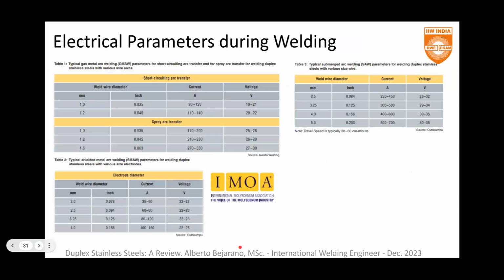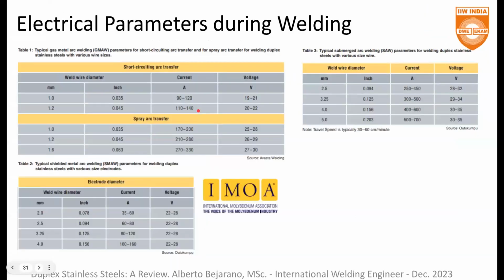About the electrical parameters, which means basically voltage and current, we have a lot of information. Of course, if we are consistent with everything that we have mentioned before, we have to be careful that the heat input calculated with these parameters is between the cooling rate that I need. Because remember, the heat input and the thermal properties define the cooling rate. The cooling rate defines the final metallurgical properties. These metallurgical properties define the behavior of my duplex stainless steels in front of a corrosive environment.